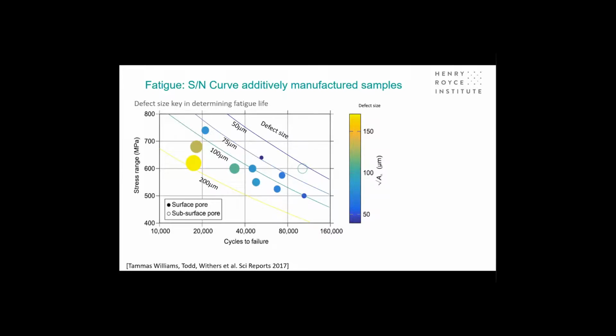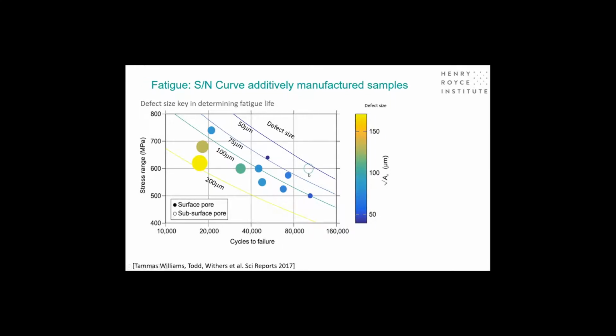those fatigue lives, showing them as a function of the critical defects, the filled samples are surface pores. The open circle here is a subsurface pore. We can see that the lifetimes of the additively manufactured parts correlate very nicely with the size of the defects. So larger defects cause shorter fatigue lives, and we can now understand the fatigue life on the basis of the defect distribution. And we can also see that on the whole, most of the failures occur from near surface defects rather than defects in the interior.